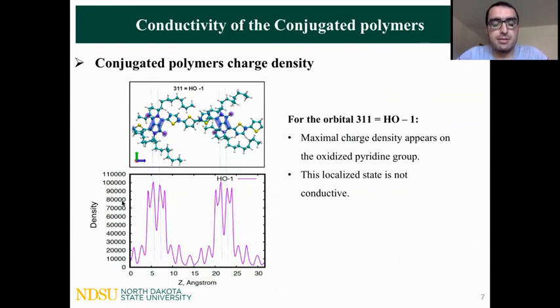So in the coming slides, we investigate the charge density from, again, the frontier orbitals, HOMO minus 1 to LUMO plus 1. This is for orbital 311, HOMO minus 1. As you can see, the maximum charge density appears on the oxidized pyridine group. So this localized state, as you can see in the top figure, is not conductive because the charge is not uniformly distributed. Next, please.